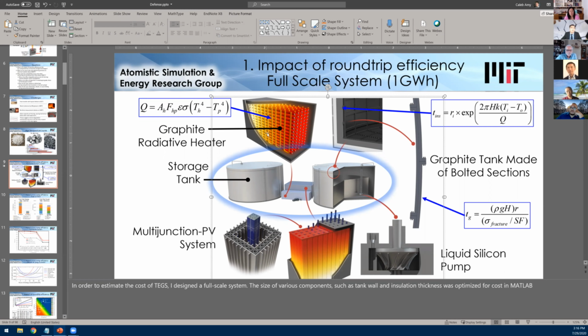There's actually a big trade-off because the thermal resistance through the wall is significant. Not because graphite is insulating, but because the heat flux is so high. So when you go from a 5 to 10 millimeter wall thickness, you go from a 10 to 20 degree temperature drop in the wall. So we're in a regime where you do need thin walls.